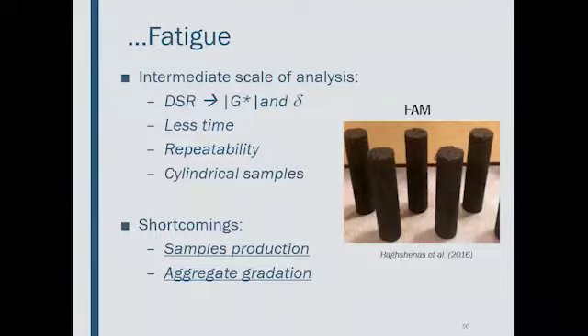And then we can work with the rheometer to get the complex modulus and the phase angle with less time, with good repeatability, and use cylindrical samples. However, there are some shortcomings. For example, about sample production, it's sometimes not easy to get the samples from the asphalt concrete. And also the fine aggregate that we use in these mixtures will impact the results, so it can change depending on the mixture that you are working with.